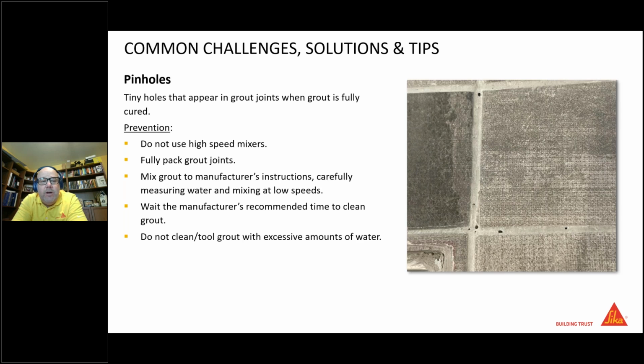But prevention in here, do not use high-speed mixers. We don't want to use a high-speed mixer because we don't want to create air entrapment inside that grout prior to using it, because what happens is we mix it, we get air entrapment in the bucket, we put it out on the floor, we smear it in. Some of those air pockets are going to be below, which is really indicative to the picture that you see right here, and they're going to pop, or as it starts to cure and shrink, you're going to end up with pinholes as you see in the picture there.